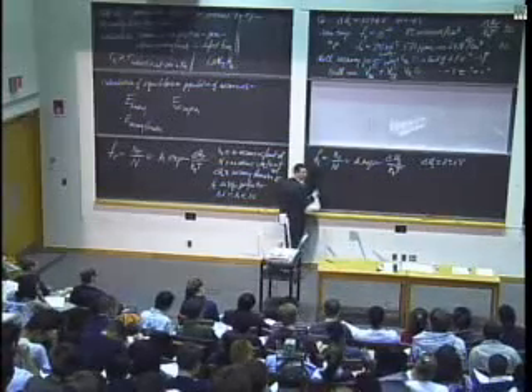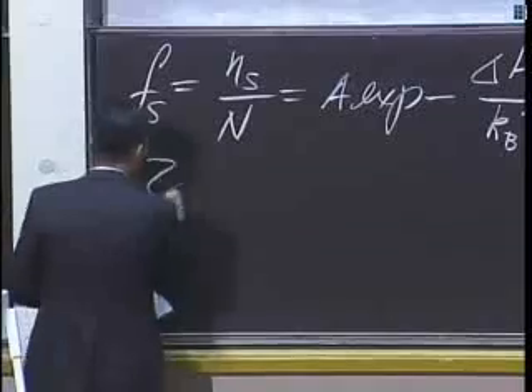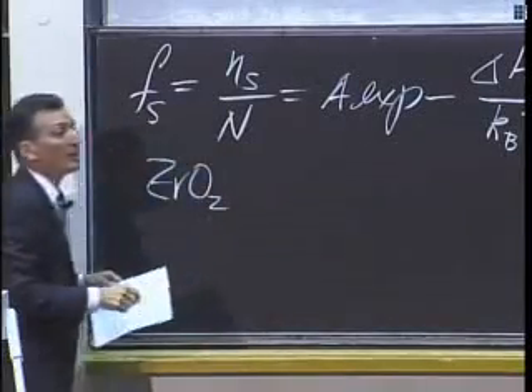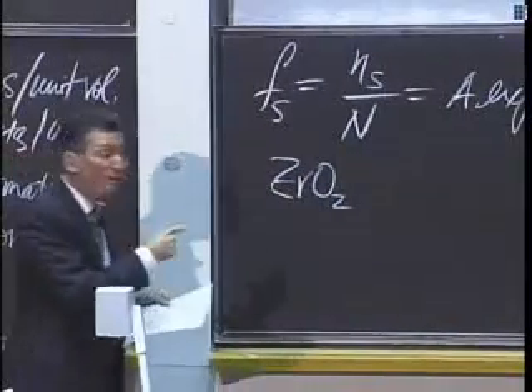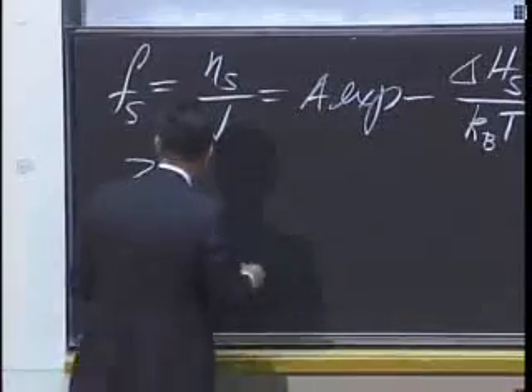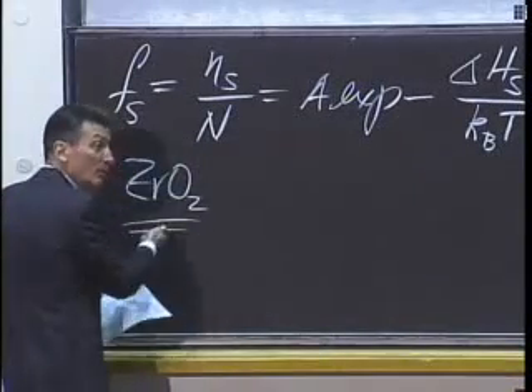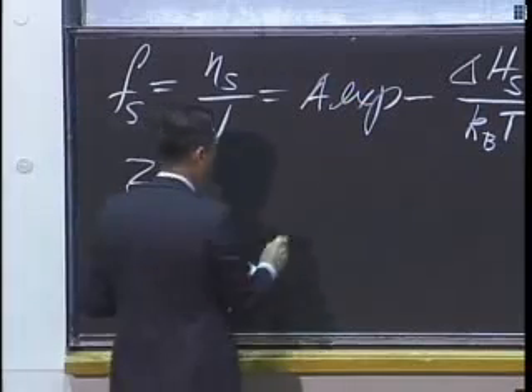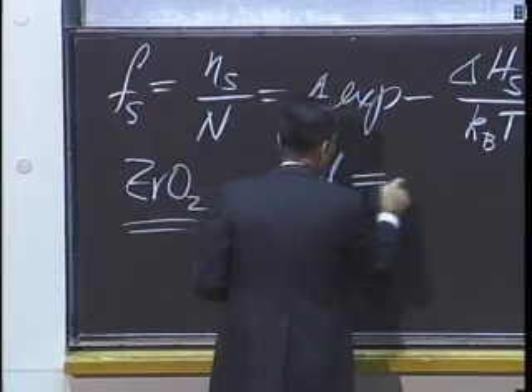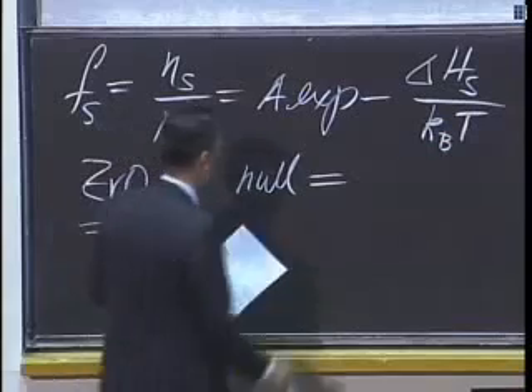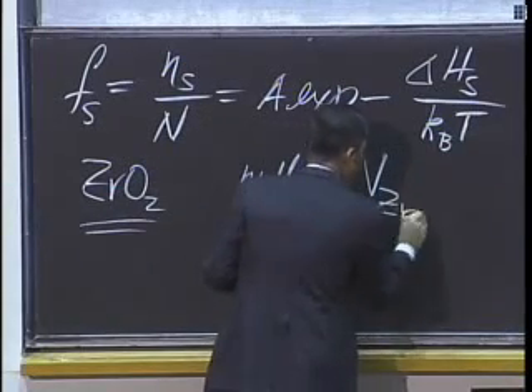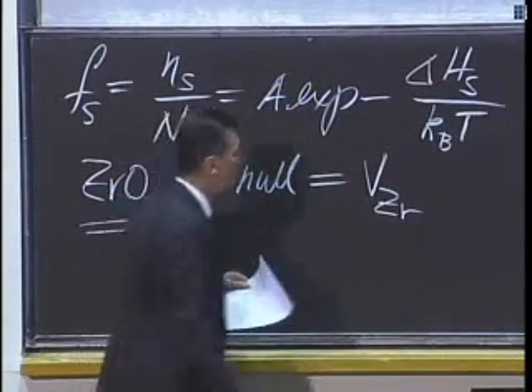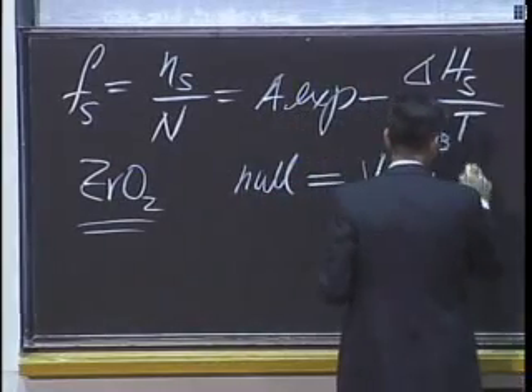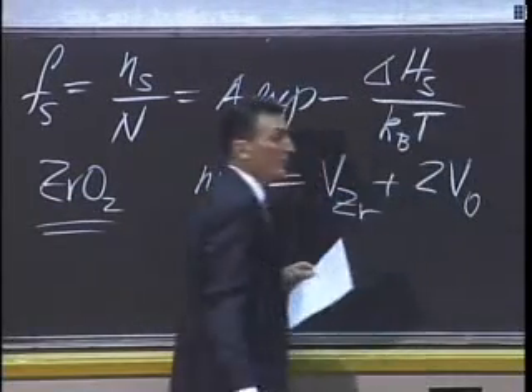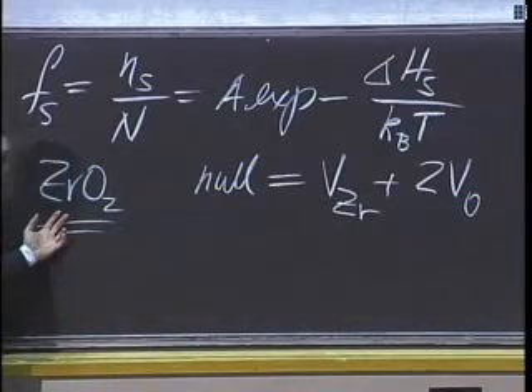I want to show you one other one. This is what's going on in the oxygen sensor of your car. It's zirconia. And I'm going to show you later how you manage the defects in zirconia to advantage. So how do I make a vacancy in zirconia? The dominant vacancy is Schottky. And I'm going to write again, null. I'm going to dissolve nothing into zirconia. So I'm going to make a zirconium vacancy and 2 oxygen vacancies. I have to preserve the stoichiometry of nothing.